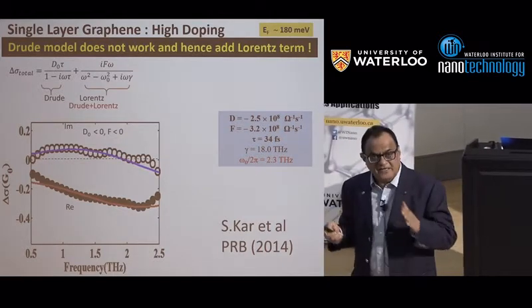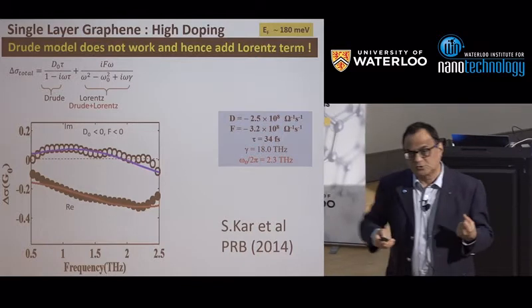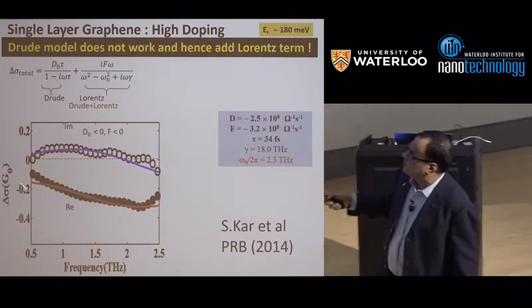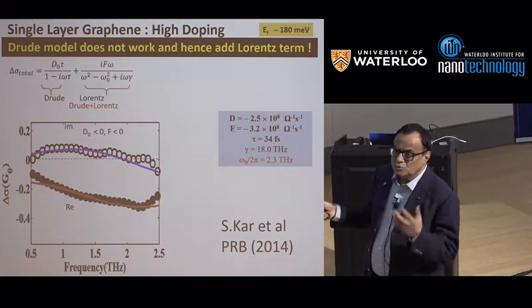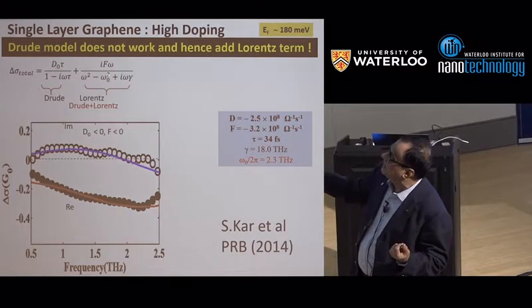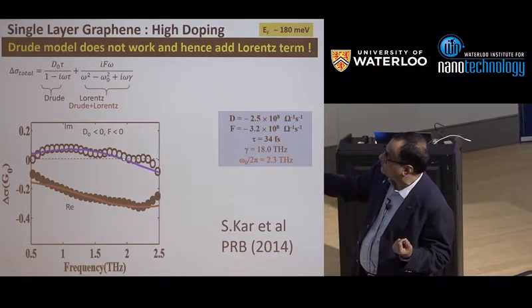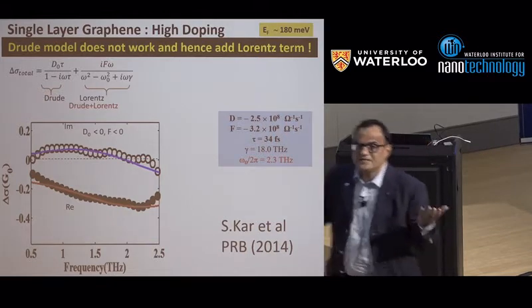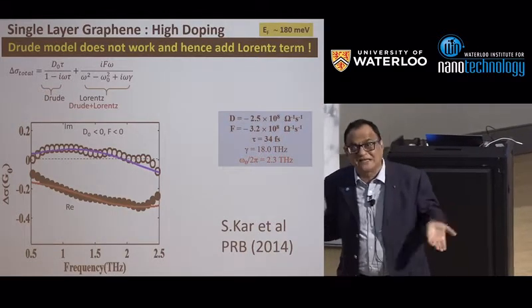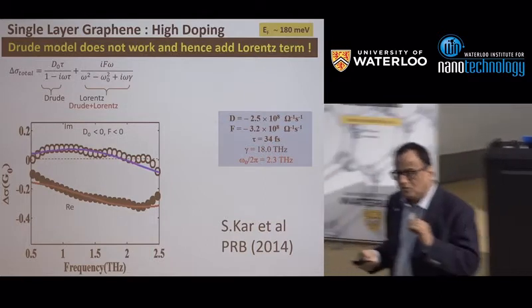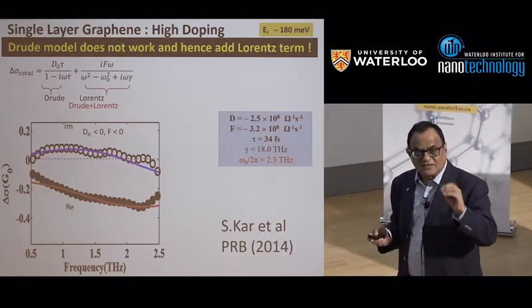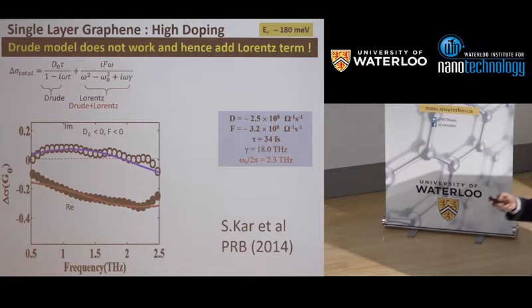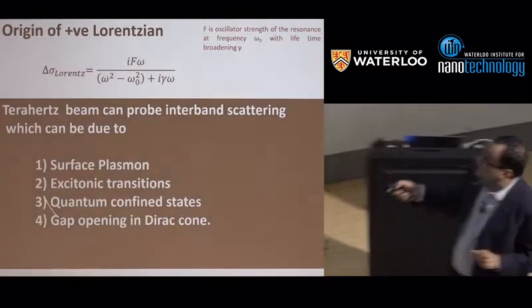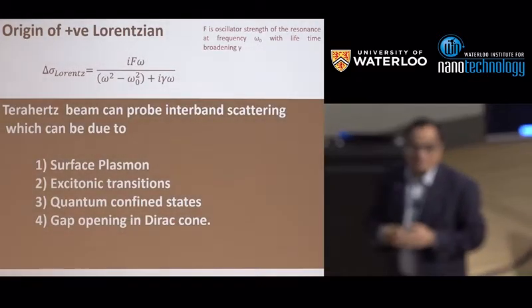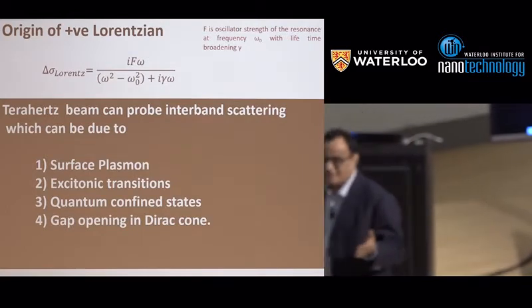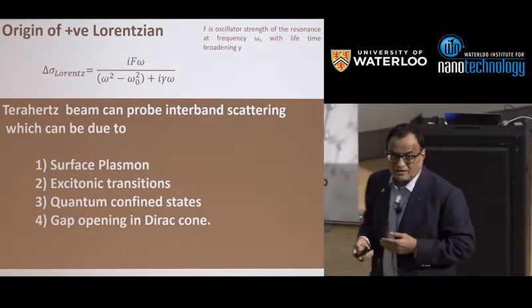And we did that because other groups had also done it, and lo and behold, it beautifully explains. But there is no understanding why there is a resonance frequency, which is a crossover here. Why this term? Where is it coming from? Where is the Lorentz oscillator strength coming from? So till now, there is no clarity on what is the origin of this Lorentzian, but it fits. We gave various possibilities and all these were ruled out because it does not vary with laser power. All that we ruled out for graphene.